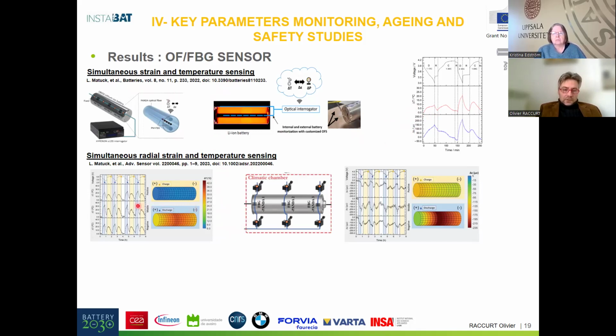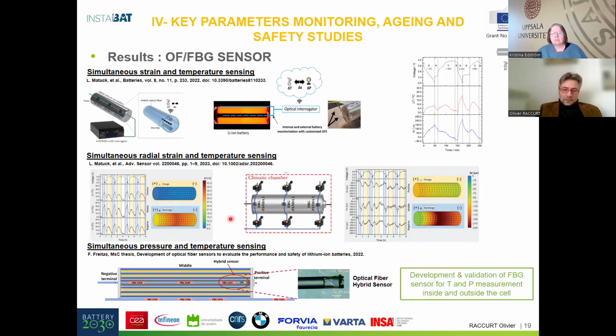Another work is with the same kind of FBG sensor to monitor simultaneously the thermal behavior of the cell during cycling and the displacement or the mechanical properties of the casing. We can access the map of these parameters during cycling simultaneously, in this case with three sensors along the cell.